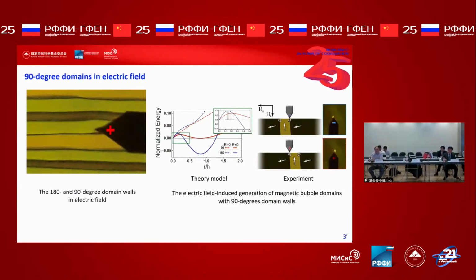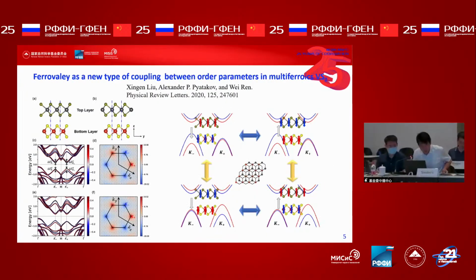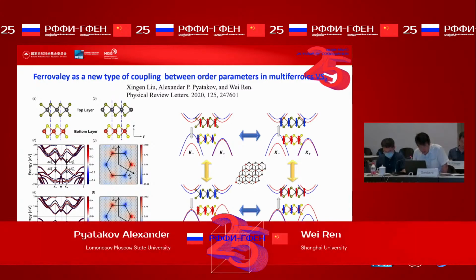My name is Wei Ren from Shanghai University. I'm going to present the following part. We have found that ferroelectricity and anti-ferromagnetism in bilayer VS2 are coupled together by ferro valley to achieve electrically controlled magnetism. One can design switching of 4 different ferroelectric antiferromagnetic configurations, which provide a new possibility for realizing multi-state storage. From our further investigation, this is not a special case only for bilayer VS2, but is quite universal in other bilayer materials as well.